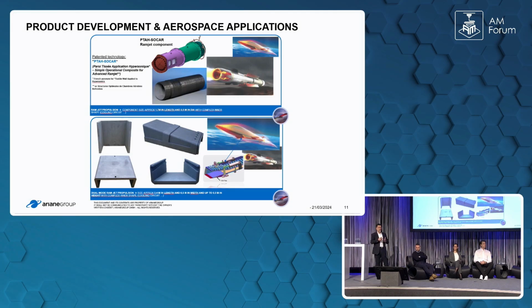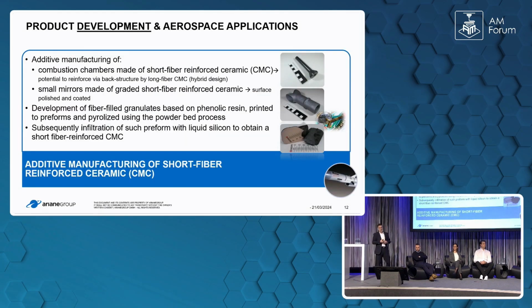We create cooling areas in the textile technology or during the textile processing, and then do the ceramization, and afterwards we have an actively cooled ceramic part which can really work at these temperature regimes. I'm talking about 2000, 2200 degrees C, something like that. But we also worked a little bit, to be honest, on 3D printing, additive manufacturing. Here a colleague of mine did a small development program made out of short fiber reinforced CMCs.